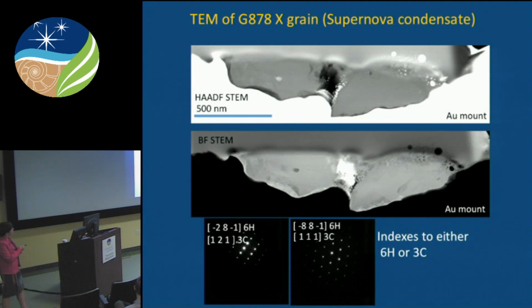Taking a look at the next grain, so that first grain was a mainstream grain, originated in an asymptotic giant branch star. This one originated in a supernova. It's referred to therefore as an X grain. It has sort of 2 lobes in this cross section, and from the HAADF image you can see it does contain subgrains as well. So there's a bright subgrain, meaning higher atomic number on average than silicon carbide. There's a dark one, so that's low atomic number compared to silicon carbide.